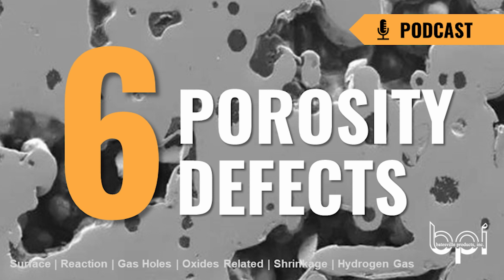If the criteria is a good surface finish, the internal doesn't matter, right? So the hydrogen porosity is never on the surface. Shrink can be, and shrink typically is. So if you want to eliminate your shrink, or you have a corner that needs to be good where you don't need shrink in the corner of the casting, sometimes gas level is okay. Pretty much a standard practice in permanent mold, depending on certain parts, to add some gas in some form or another. I've seen potatoes, I've seen 2x4s, I've seen pretty much everything used to add a little gas into the part.